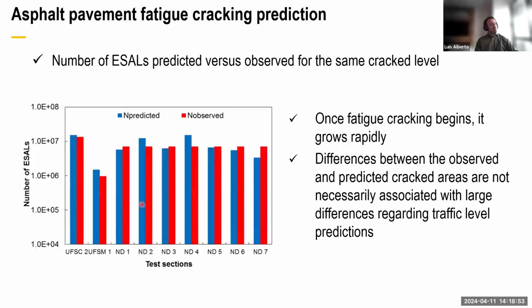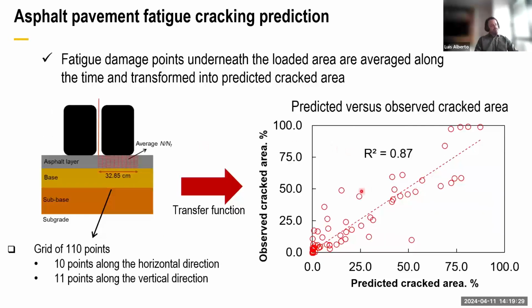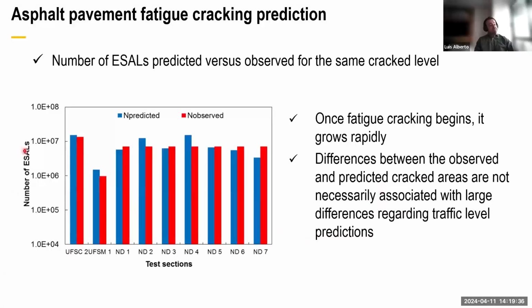Even though we have good data here, it's important to take a look at this data by considering the time. So we have some validation test sessions. They are not included in calibration. And here we have the number of load repetitions for different test sessions, and for the same damage level, cracked area level, we compare the predicted load repetition versus observed load repetition, and you can see that you have very nice predictions. Even though we have some outlier here regarding observed versus cracked, when you consider the time or the number of repetitions, they are very close. For pavement design, this is very important. For performance prediction, this is very important.